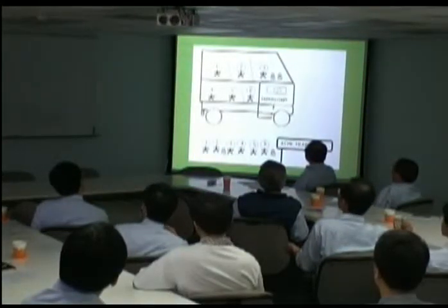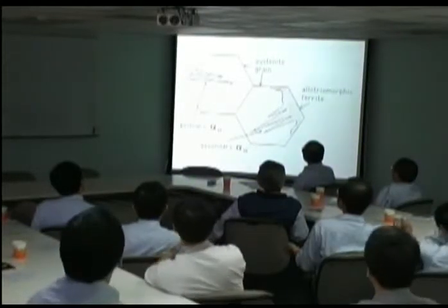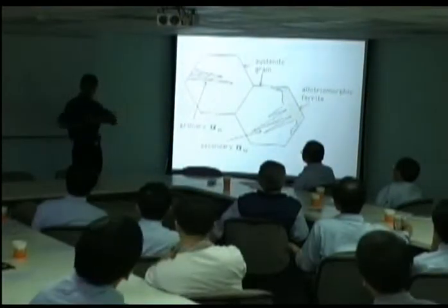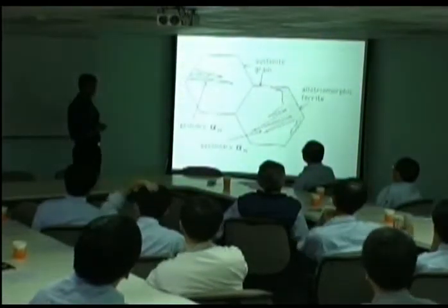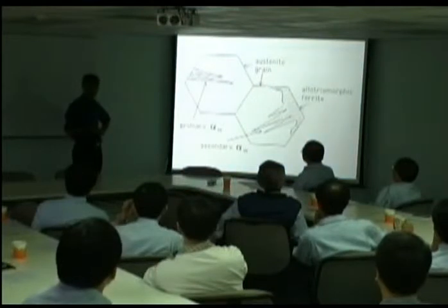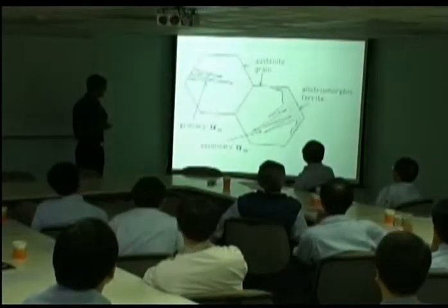So I want to now explain to you the difference. We've explained the difference between bainite and martensite. I want to explain the difference between bainite and Widmanstätten ferrite. Widmanstätten ferrite grows at a higher temperature, frequently above the T0. So there's no question that it can grow without diffusion. You've all seen micrographs of Widmanstätten ferrite, and it looks like a thin wedge shape. Sometimes it grows directly from the austenite grain boundaries, at other times it grows from layers of ferrite present at the grain boundaries. But this thin wedge shape is important.